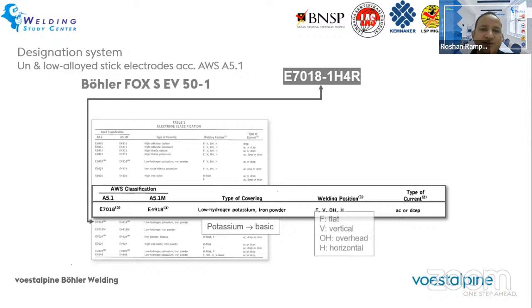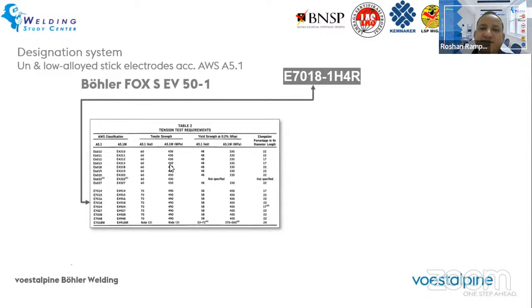And based on the AWS classification, 70 indicates that it is a 70 KSI type of electrode in which the minimum tensile requirement is 490 megapascal, which is 70 KSI, and yield requirement is 400 megapascal, which is 58 KSI, and elongation is 22. So Table 2 in AWS 5.1 indicates the mechanical properties requirement for the 70 KSI category. If it is 60 or 80, then the mechanical requirements are different.